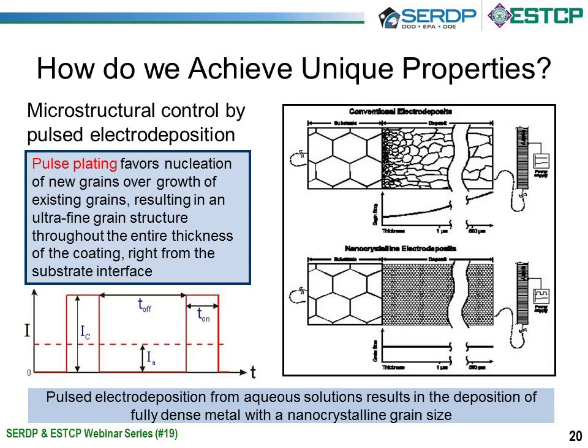So how do we achieve these properties? The materials that we work with are made via electrodeposition. And the way we control the microstructure is through pulse electrodeposition. Pulse plating favors nucleation of new grains over growth of existing grains, so it results in an ultrafine grain structure throughout the entire thickness of the coating, right from the interface substrate.